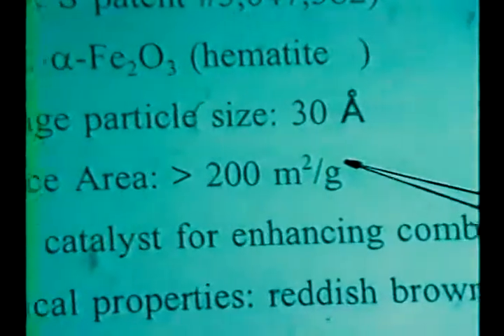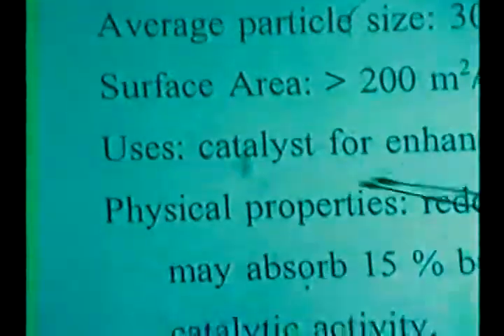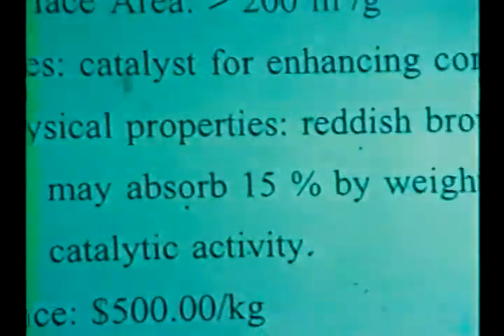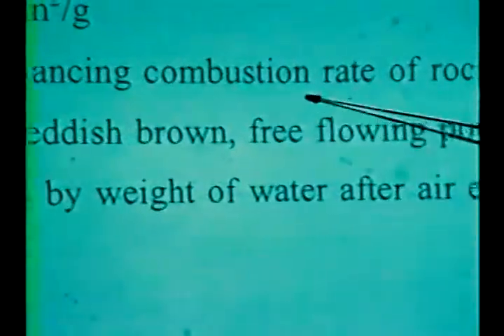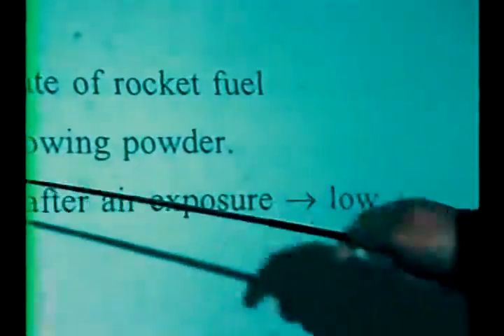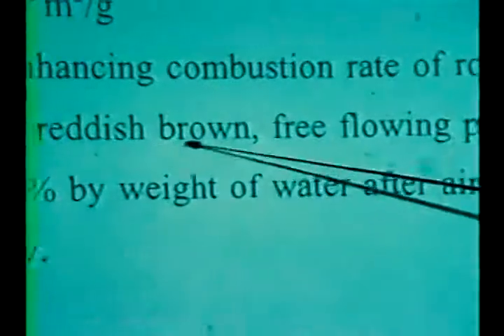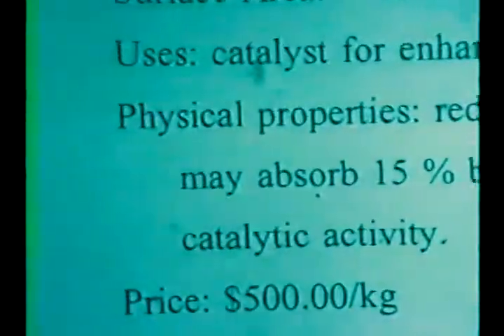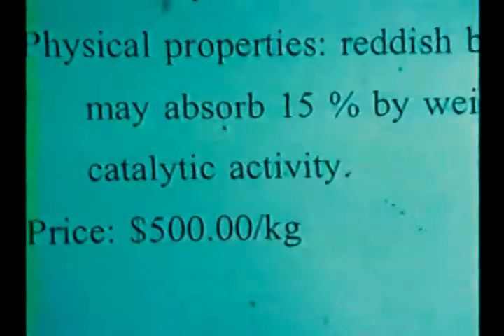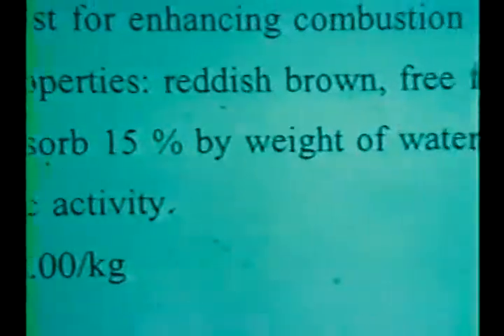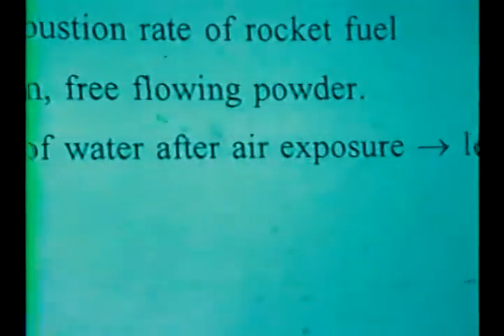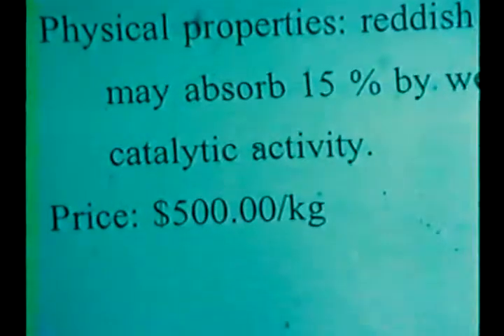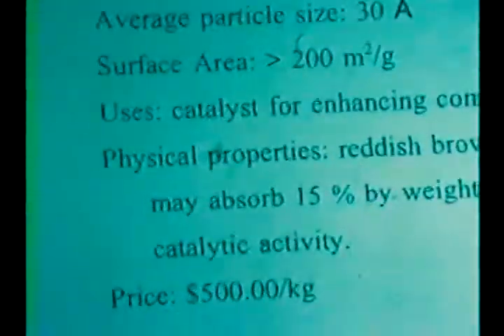Very small particle size, 30 angstrom, and large surface area. It was originally used for enhancing the combustion rate of rocket fuel. It's a reddish brown, free flowing powder, and absorbs a lot of water. But water is really bad for the activity. The price is very high, over $500 per kilogram. But it is very interesting material.